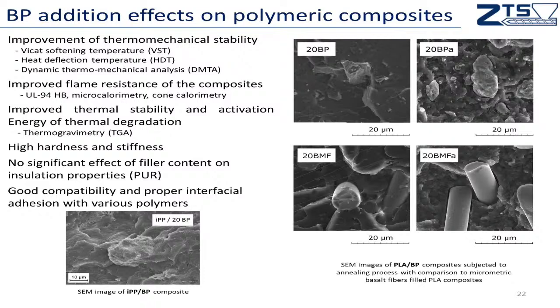So the thermal treatment of the amorphous materials is realized in order to achieve the crystalline structures. We can see that adhesion in the case of the basalt particles is not totally lost. There are no pull-outs of the fillers. In the case of the basalt fibers, the adhesion was totally lost. The properties were much worse in comparison to the basalt particle materials.